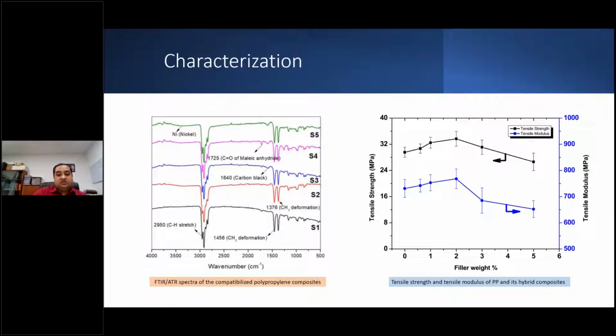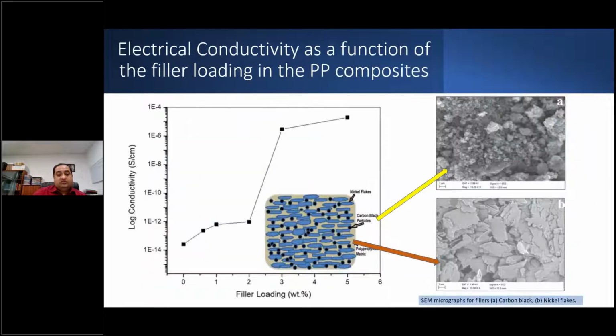But on the other hand, once we measured the electrical conductivity of the composites, and it is plotted over here as a function of the filler loading, it showed that an enhancement in the electrical conductivity was observed due to the presence of this electrical conductivity path, which was generated by utilizing different shaped fillers. We have the carbon black particles along with the platy nature of the nickel flakes, with the help of which we were able to develop the conductivity path within the composites, and based upon that we were able to use these composites.